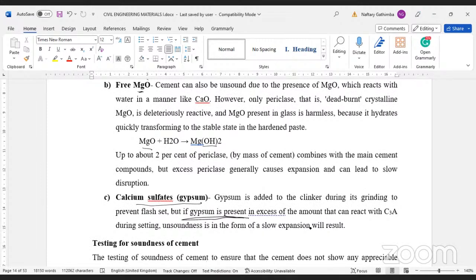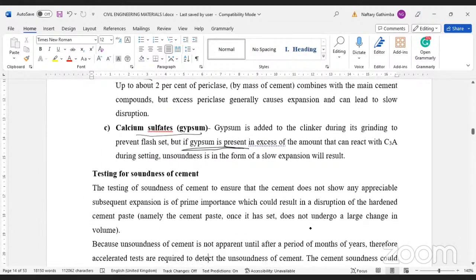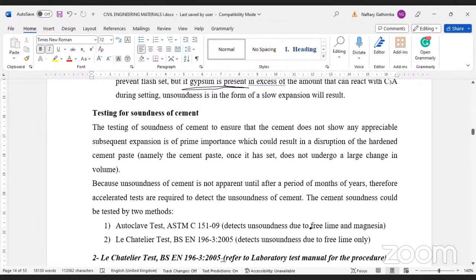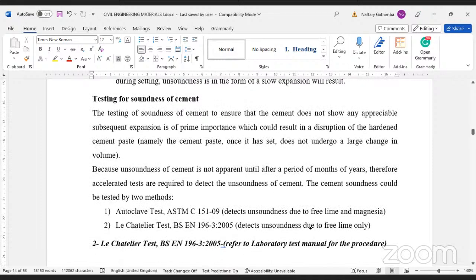Okay. Now, to test the soundness of cement, I'm moving a little bit faster here. There's not much chemistry. There's a laboratory test that we do. And there are two tests you can use, either the American ASTM, which refers to the American Society for Testing and Materials, or you can go with the British or Eurocode. For us, again, we follow the Eurocode. We use the Le Chatelier test. Of course, you're going to do the test in the lab.